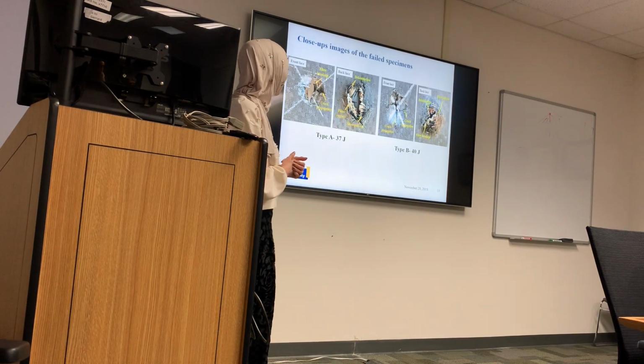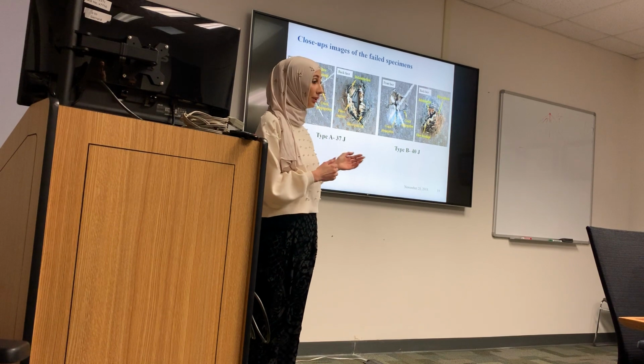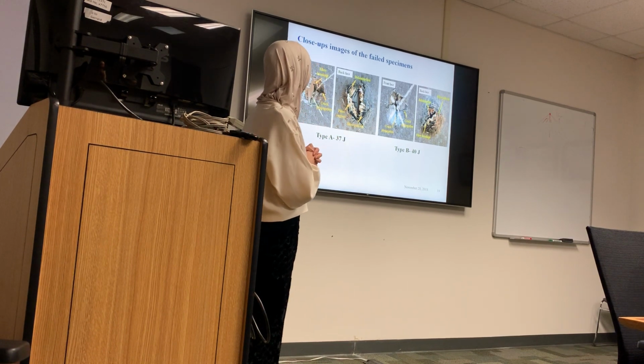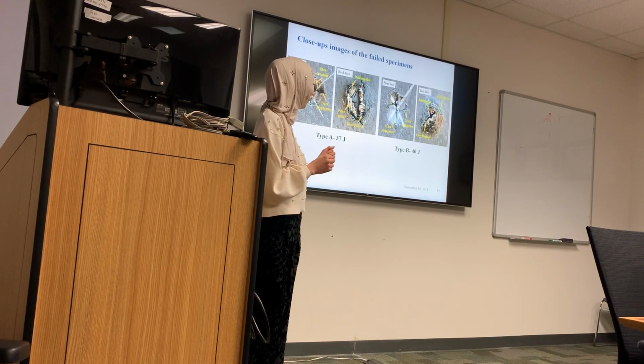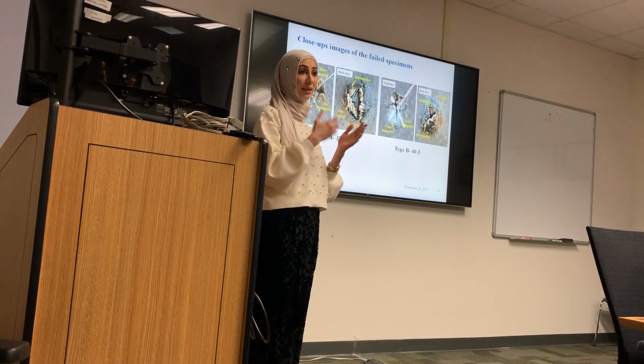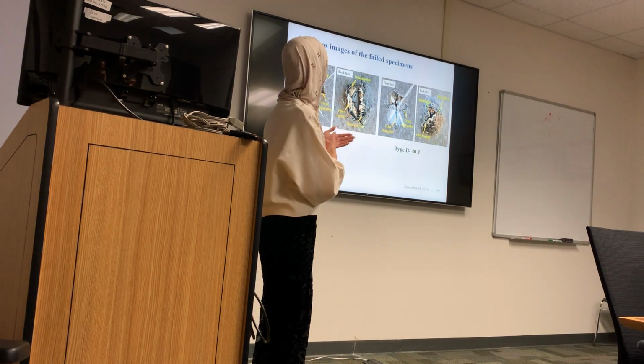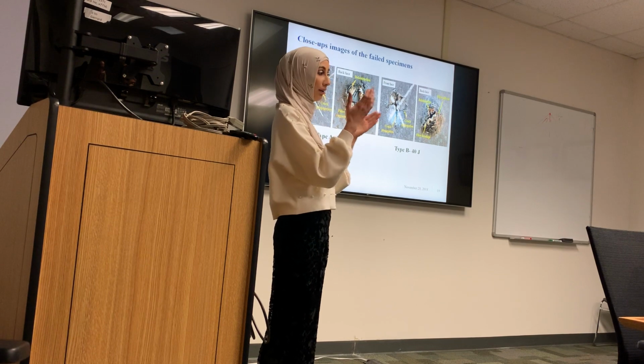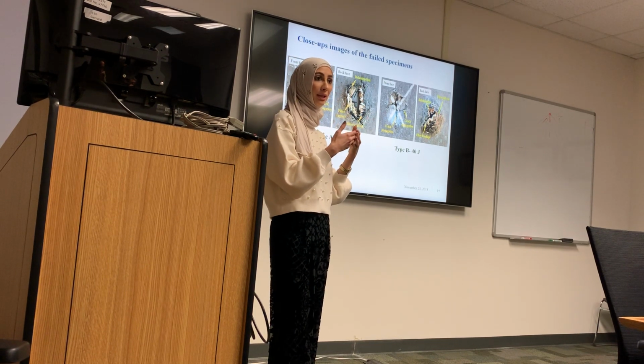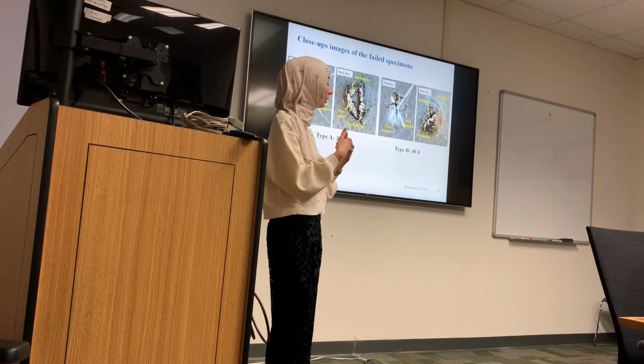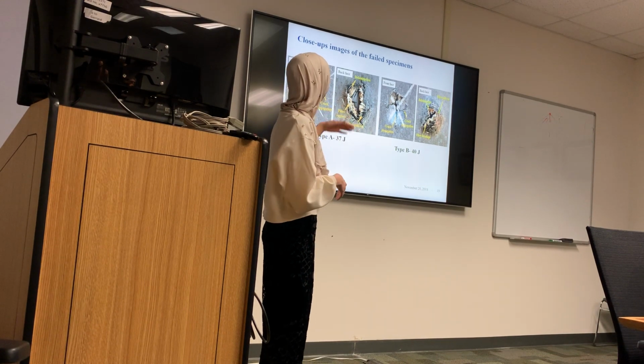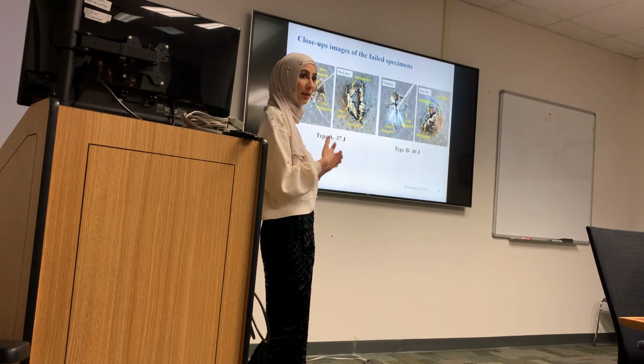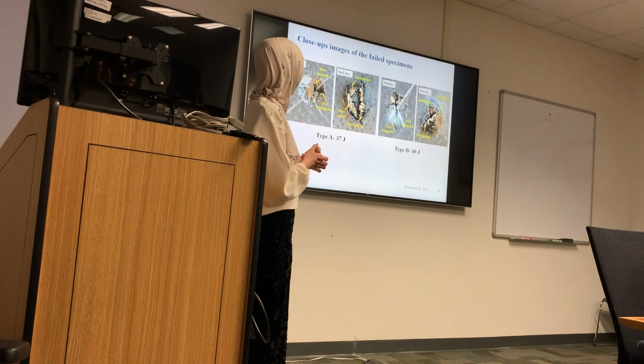We see here close-up pictures of the penetration that happened at the penetration level, for type A and type B. We have to consider that when the impactor hits the composite, the front face facing the impactor experiences compression load, so we see the fibers were buckled. And on the back face, the surface experiences tension,